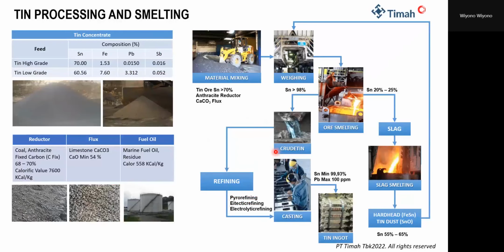Okay, this is our smelting process. In the left corner, this is the composition of tin concentrate. Here we have two different grades of tin concentrate. The first is tin high grade and the second is tin low grade. The tin high grade has a bigger composition of tin than the lower, and the impurities will be higher in the low grade than in the high grade.